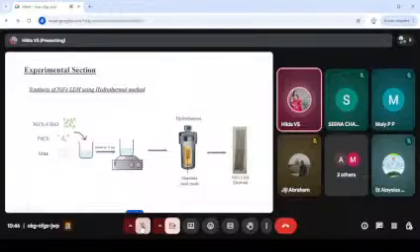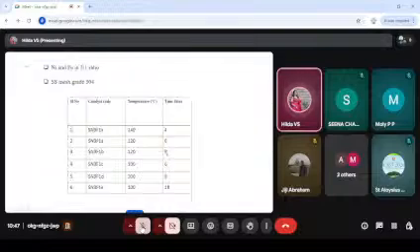until it obtains a uniform concentration, and is transferred into a Teflon lined autoclave. Along with that, I use stainless steel mesh as a substrate for the growth of this nickel iron LDH. This is the obtained electrode, and it is then washed with acetone and water and dried at 60 degrees Celsius overnight and used as an oxygen evolution reaction catalyst. Nickel iron is used in a 3:1 ratio, which is the optimum ratio for the best activity. And these are the series of catalysts I prepared using different time and temperature.